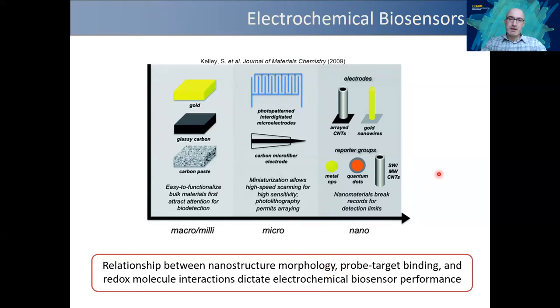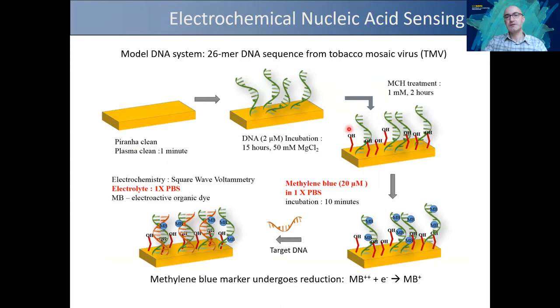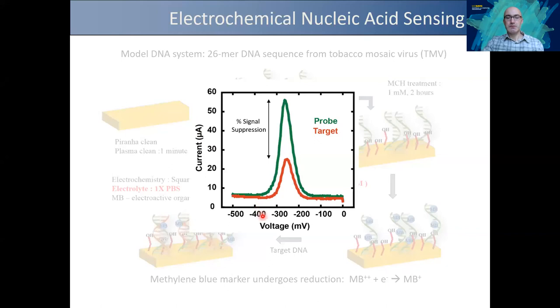And in all of these, basically, the nanostructure morphology has a big influence on both the electrochemistry and also the probe target binding. So let me give you a quick crash course into how the nucleic acid sensing works in our case. You have a planar electrode, you have your probe DNA for capture, think about, again, a DNA microarray. You backfill with mercaptohexanol to passivate the surface and also to orient the probes up so they are more accessible. Now you can introduce methylene blue, which is a redox molecule that associates with the bases. Now, if you use an electrochemical protocol, we use square wave voltammetry, and reduce the methylene blue, basically you give it an electron, you get a probe signal. This green signal basically tells us that we have the probe molecules and the methylene blue associated with them.